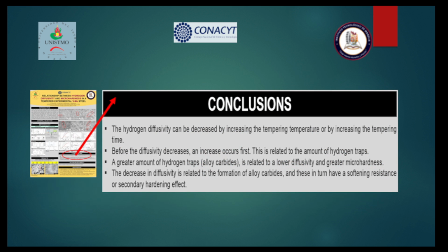In conclusion, we can say that the hydrogen diffusivity can be decreased by increasing the tempering temperature or by increasing the tempering time. This is related to the amount of hydrogen trapped. A greater amount of hydrogen trapped is related to a lower diffusivity and greater microhardness. The decrease in diffusivity is related to the formation of alloy carbide, which in turn has a softening resistance or secondary hardening effect.